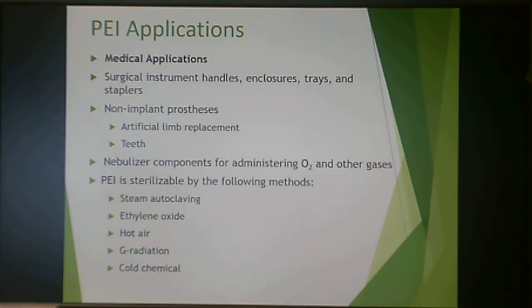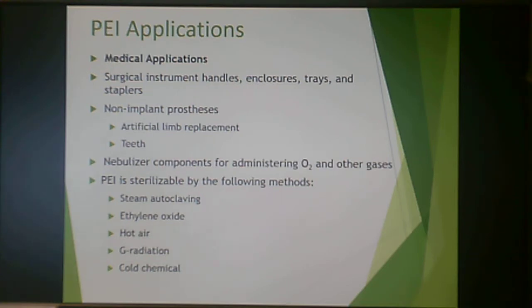It is often used for medical applications like surgical instrument handles, enclosures, trays, and staplers — things that have to be reused and sterilized. It can also be used for non-implant prostheses like artificial limb replacements and teeth. It's used for nebulizer components for administering oxygen and other gases, because it can be sterilized by pretty much any method used in the medical field: steam autoclaving, ethylene oxide, hot air, gamma radiation, or cold chemical — it withstands all of that and comes out just fine.